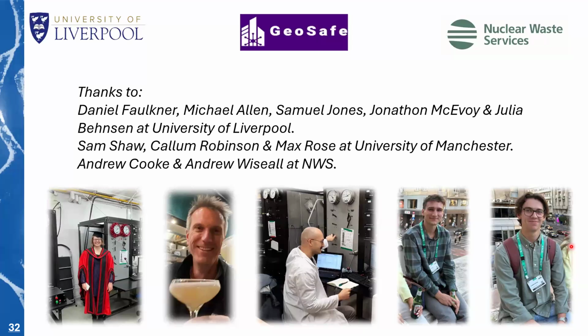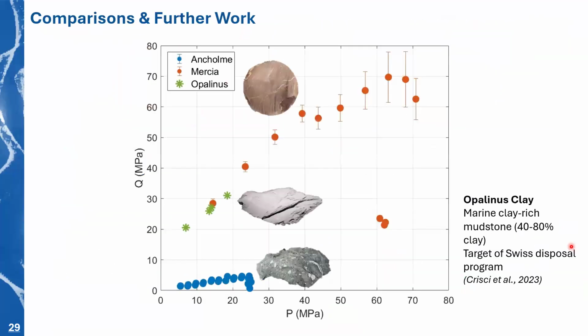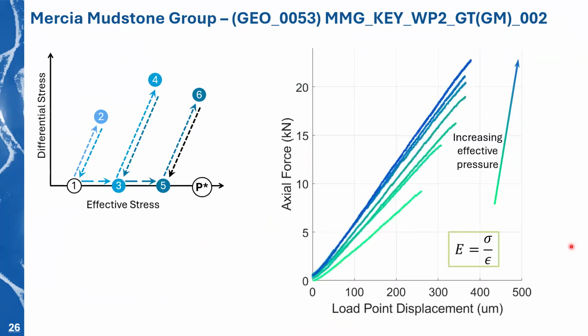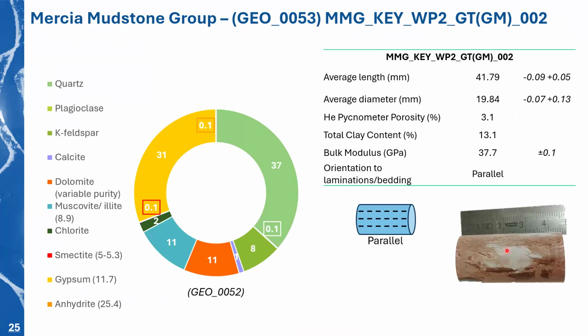So for choosing the samples, at the moment, it's really difficult to get a sample prepared and put into the rig. So I've put 2 of the Mercia ones into the rig, and I've shown you both of them in this presentation. But because it's so variable on the scale of the cores, it's hard to know exactly what you're going to get when you drill into it, if I'm honest. Because, for example, the small core that I showed, in this one, it varies within the core. So like I have reduction spots, I have gypsum veins, I have such a huge variation on the scale. It's quite hard for me to target it to be trying to find ones that are high clay or low clay.